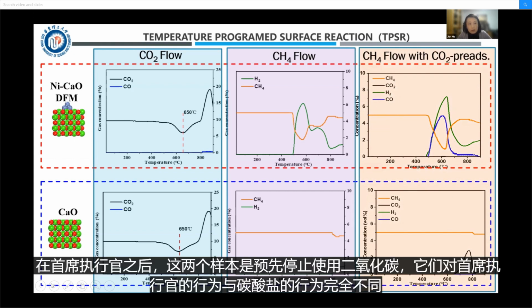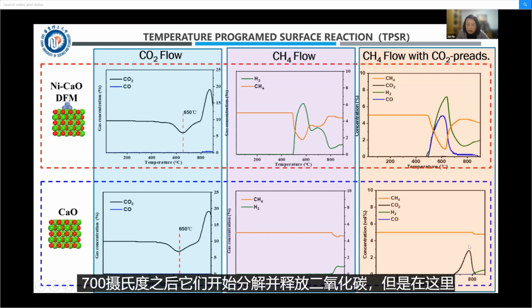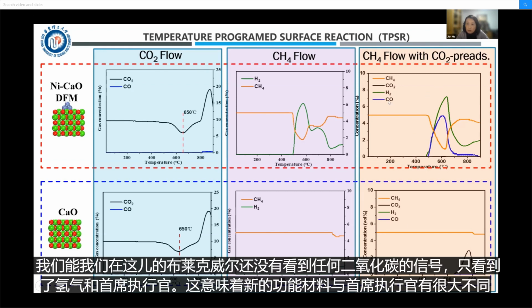Furthermore, after these two samples were CO2 pre-adsorbed, their behaviors are absolutely different. For the calcium carbonate, after 700 degrees C, it begins to decompose and release CO2. But here, we haven't seen any signals of CO2. H2 is here, the black one, and only hydrogen and CO were observed. That means the dual functional materials are quite different from CaO.